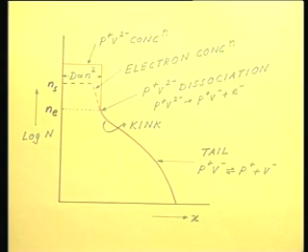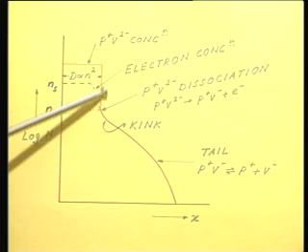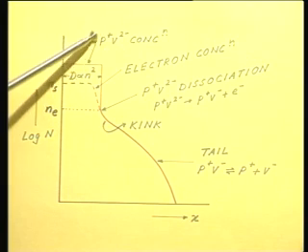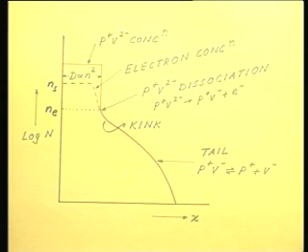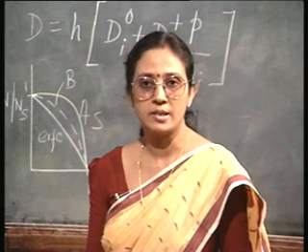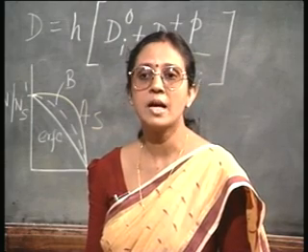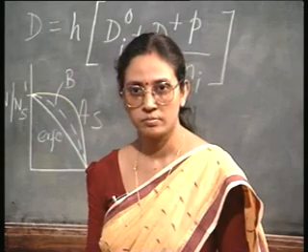As the Fermi level position changes, as it falls 0.11 electron volt below the conduction band, this pair starts to dissociate. Very simply speaking, it is something like this: doubly ionized vacancy, doubly negatively charged vacancies. That means this vacancy had trapped 2 electrons.